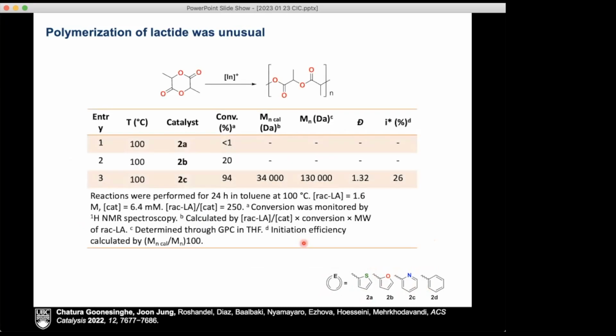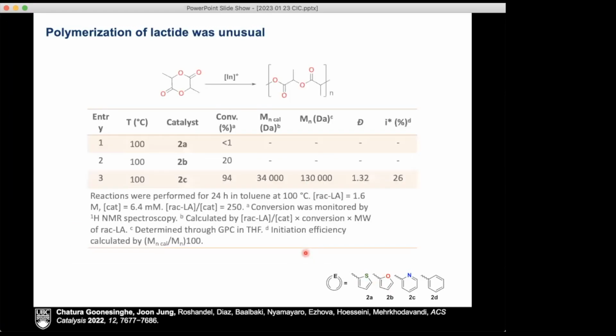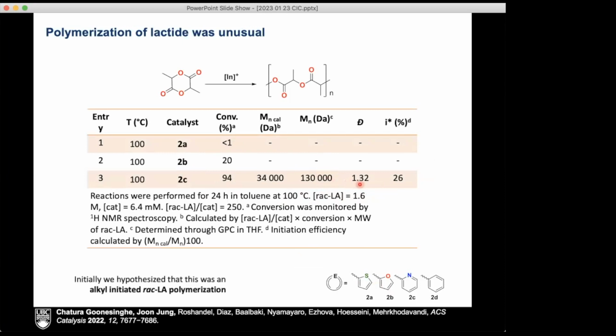What was unusual though was the polymerization of lactide. When we attempted the polymerization of lactide, neither the sulfur nor oxygen donor gave us any discernible or important reactivity. However, the pyridine compound, which remember was much slower for epoxides, gave us reactivity for lactide, and relatively controlled reactivity, with high molecular weights, relatively low initiation efficiency, but still good dispersity. And so we thought, what exactly is this material?